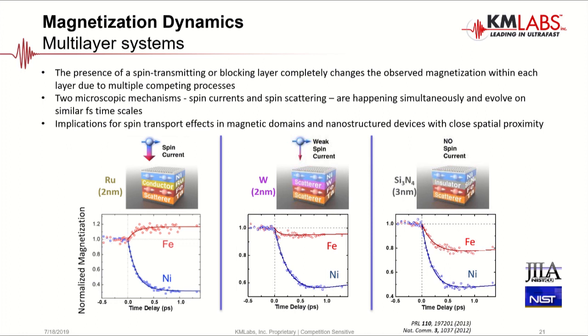And what we can pretty clearly see in the plots on the bottom is that we do in fact get very different dynamics depending on what that interlayer is. In the far left, we get an increase in the iron magnetization while the nickel decreases pretty substantially, while in the other two, we get a similar demagnetization of the nickel, but it sort of pulls or drags the iron down with it, so to speak, where we have a lesser magnitude demagnetization of the iron as well. So this tells us there's some amount of spin transport or spin coupling effects that are happening between these nickel and iron layers, even with different types of insulators or scattering layers between them.